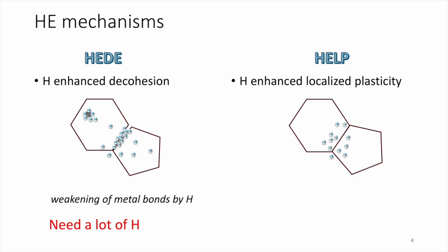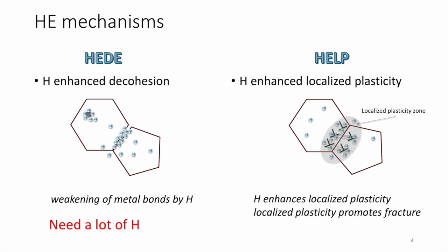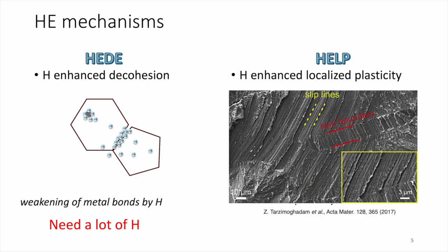The second one is called HELP, which is hydrogen-enhanced localized plasticity. The HELP hypothesis proposed that hydrogen would enhance the localized plasticity, and the localized plasticity promotes the fracture. There is evidence that hydrogen enhances the intrinsic mobility of individual dislocations. While localized plasticity does promote fracture in some materials, evidence for its role in hydrogen embrittlement usually takes the form of slip lines or enhanced dislocation densities observed at the fracture surface, or cracks observed along the slip bands. The thing is, are those observed features the cause of the fracture or one of its effects?